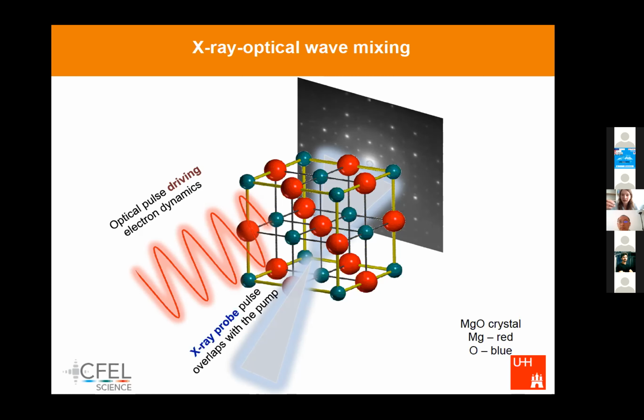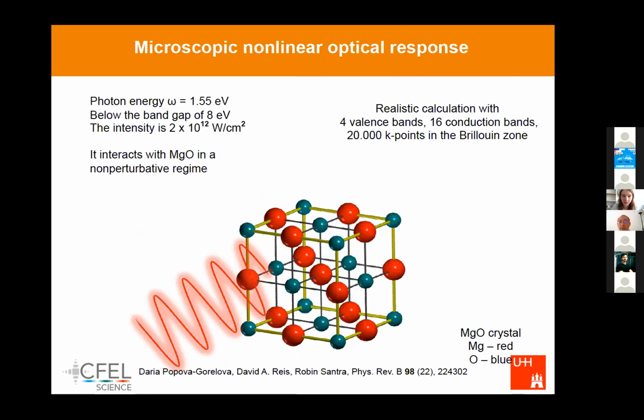So we want to see what happens to the laser-dressed electronic system on an atomic scale. How do we theoretically describe this? First, the interaction with an optical pulse. Here we consider bandgap crystals. In the case I'm going to show you, it is magnesium oxide, a crystal which is an insulator with a very large bandgap. An optical pulse with photon energy below the bandgap, but of very high intensity, drives dynamics in magnesium oxide.